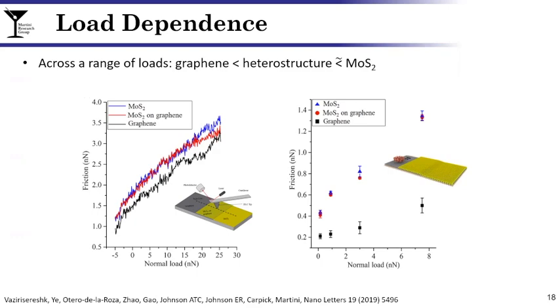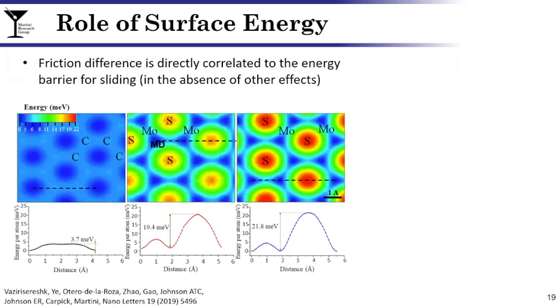To explain this difference, again, we're trying to use energy as the link between friction and atomic features. We looked at our potential energy surfaces. The colorful images are the energy maps, and the lines below them are a line profile across the high energy barrier. And we can see from our empirical potential in the MD simulations, there's a higher energy barrier for sliding that has to be overcome to slide on the MoS2 than the graphene.